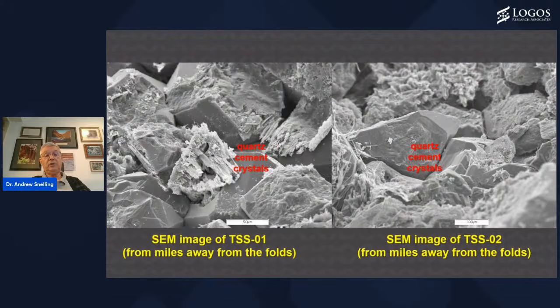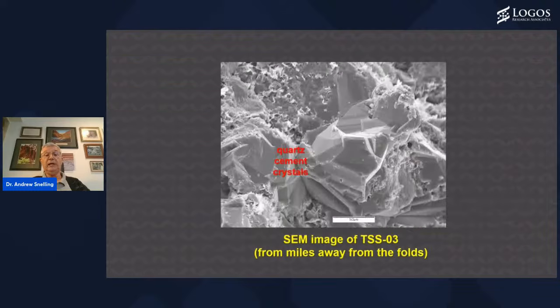Number 1, look at the beautiful cement crystals, quartz cement crystals in 1 and 2, and 3, nice crystal faces and terminations, the same miles away from the folds as samples within the hinge zones and the limb zones of these folds. The cement is still pristine with terminations and faces from the cement having grown into the pore spaces. This should not be the case if the sandstone, after the cement was formed, had been bent millions